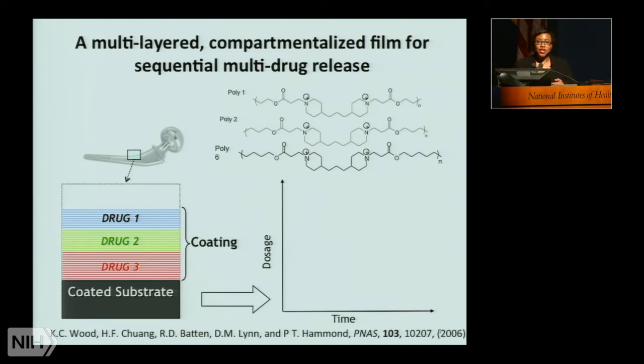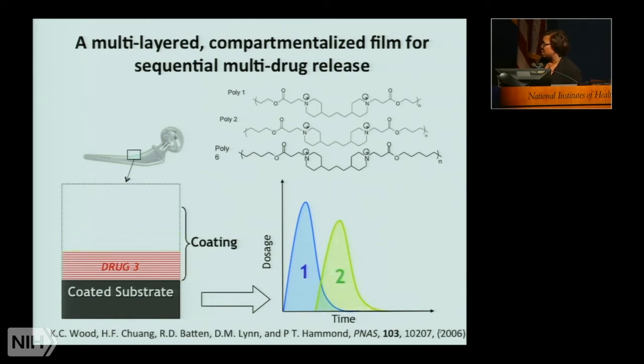Now we're actually tuning the release rates of the drug. If we're able to introduce separations between these drug layers, we can prevent interdiffusion of the drugs during the construction of the film. And with that, we can get not only different release rates for each drug, but a kind of controlled stagger or stage-wise release of each drug. And there are several reasons why this is compelling.